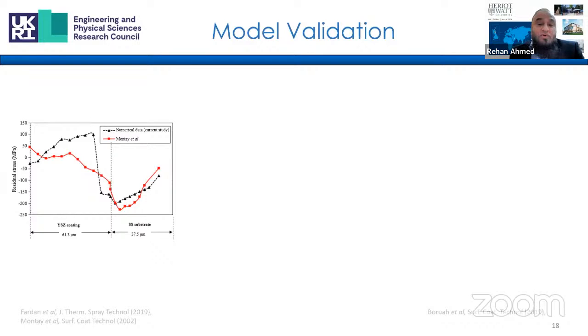And the first work here compares the residual stress of a yttrium stabilized zirconia on stainless steel substrate. There's a fairly good relation between the two, except for the high tensile stress in the coating. And this could be due to the assumptions in the model, and also yttrium stabilized zirconia is prone to microcracking, which could have reduced the residual stress from the experiments conducted by Montay.